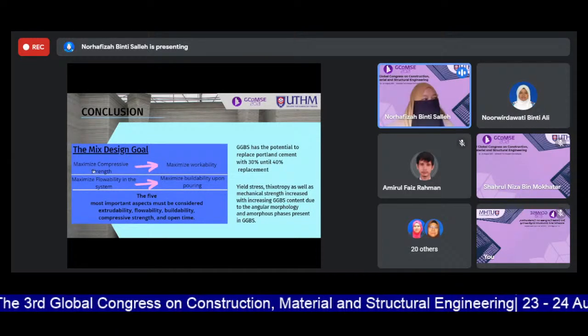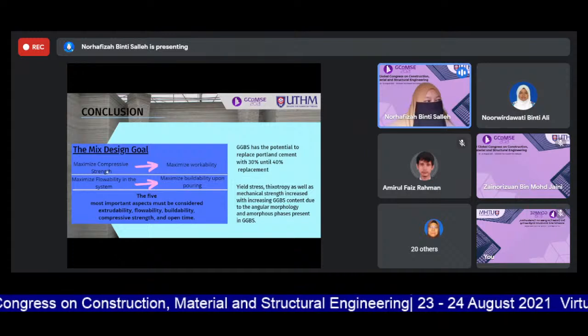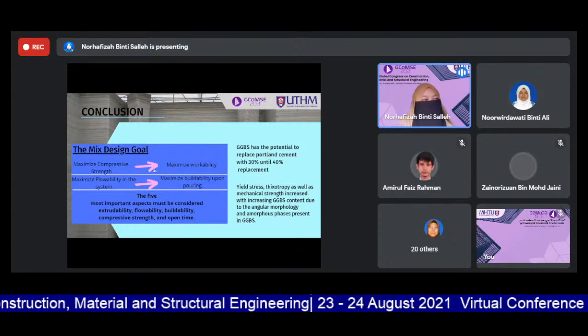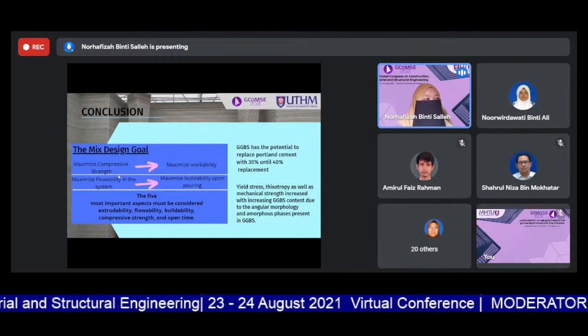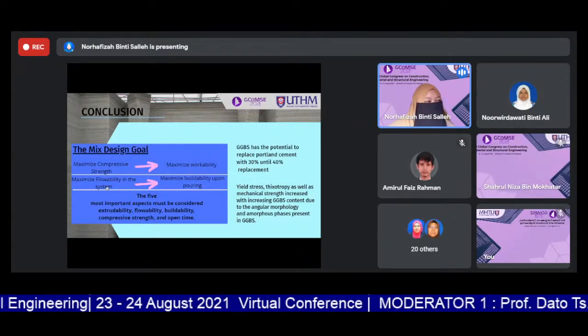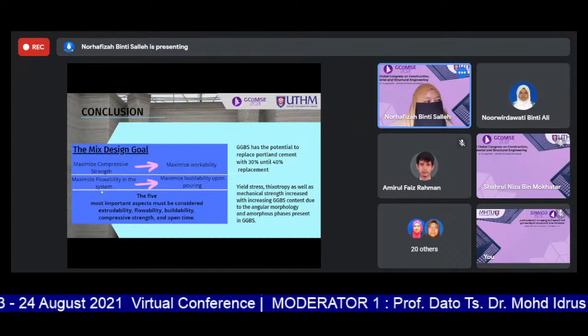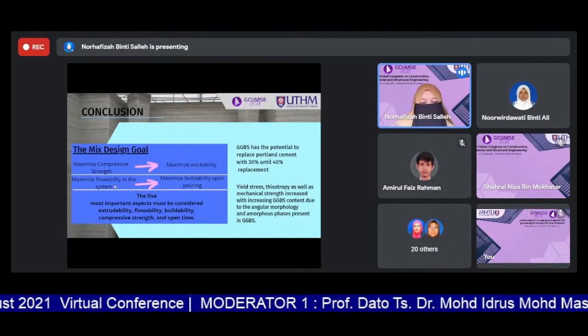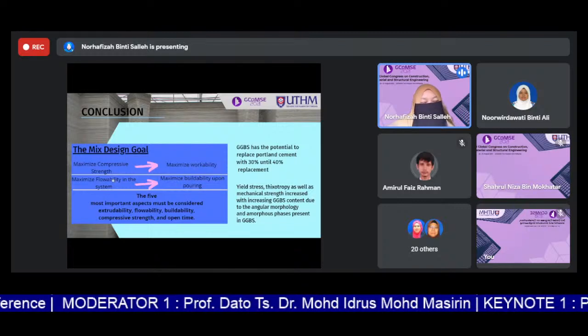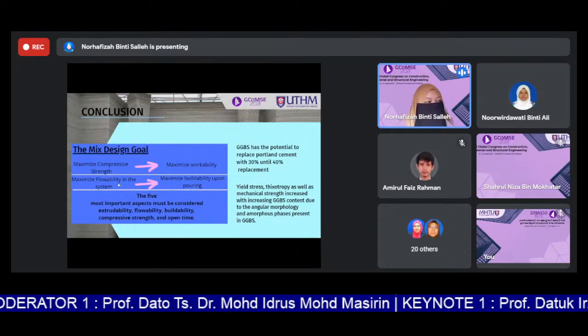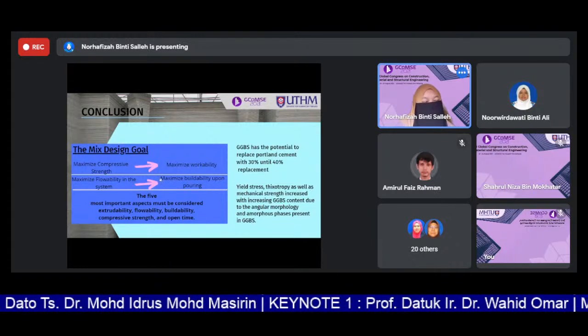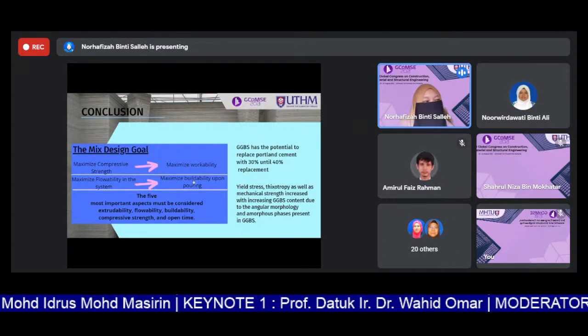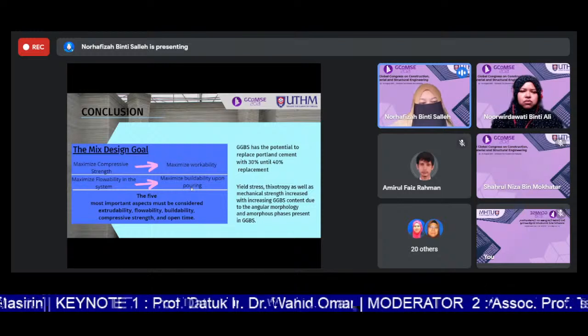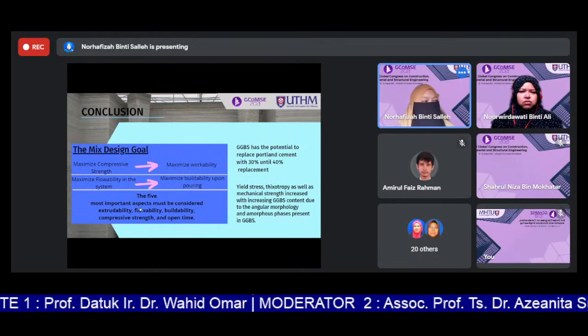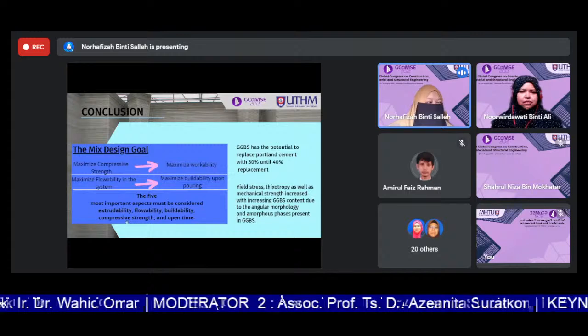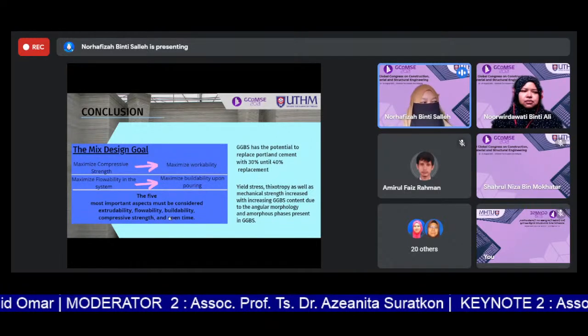All right, so for the conclusion, when we make a mix design, the goal must first be to achieve the maximum compressive strength, but we must consider the workability of the mix design, and maximum flowability in the system, to make sure the flowability is okay. But we must also ensure that the maximum buildability upon pouring is in good condition. So there are five most important aspects to be considered: extrudability, flowability, buildability, compressive strength, and open time.